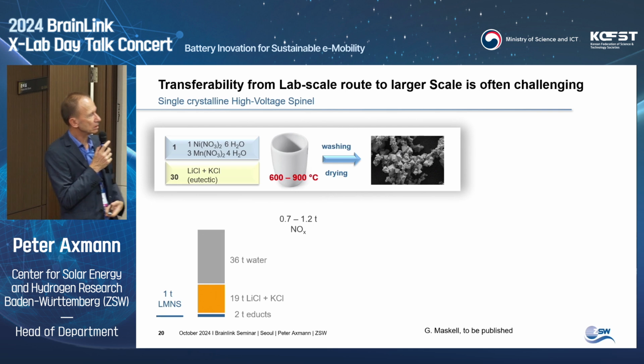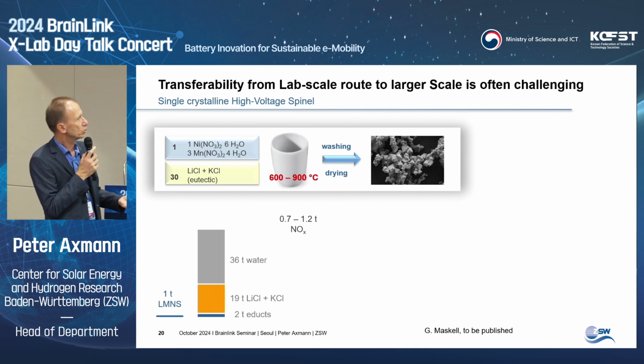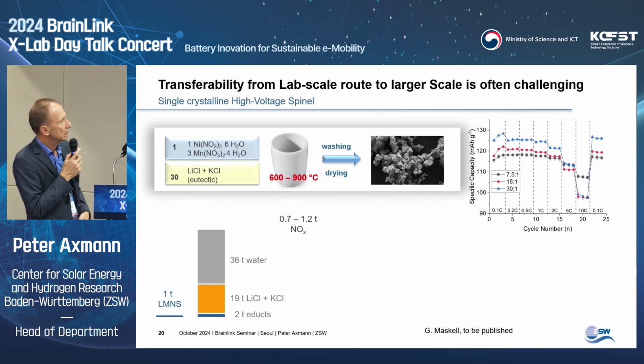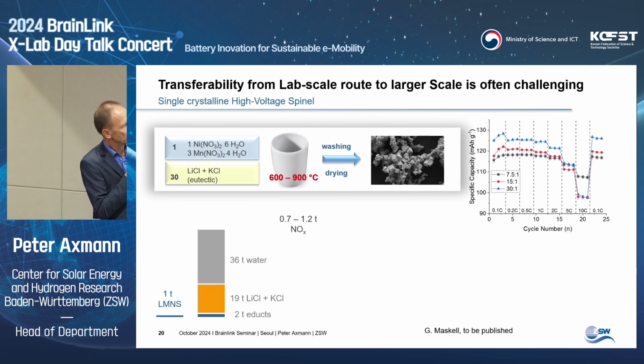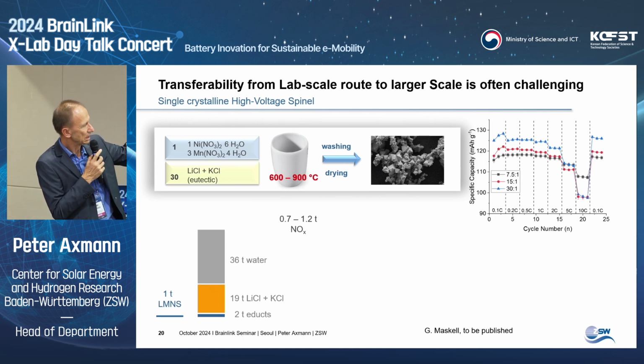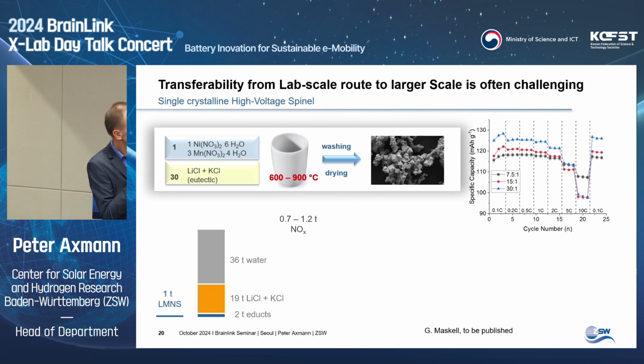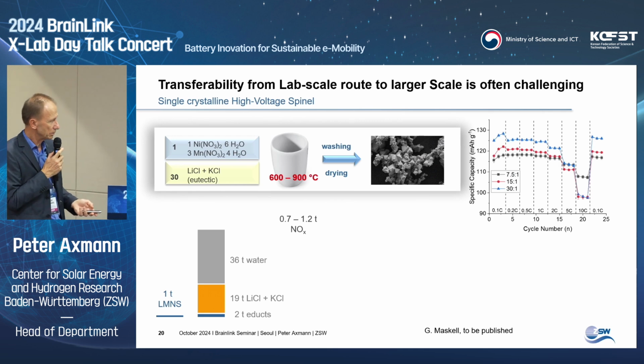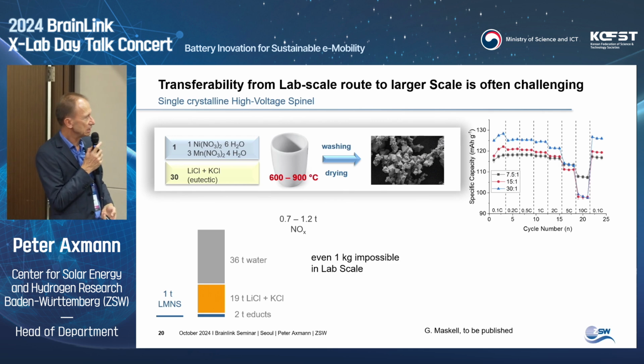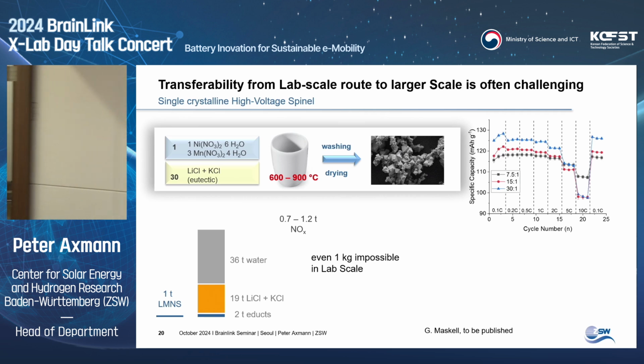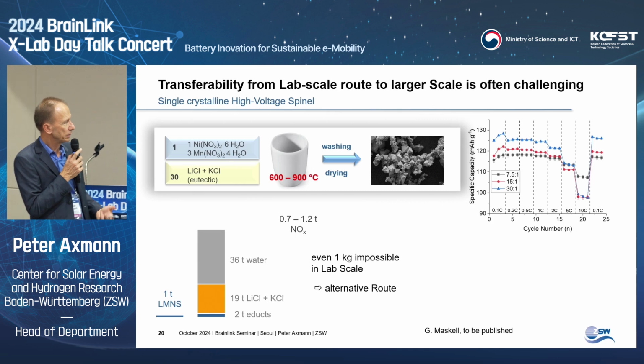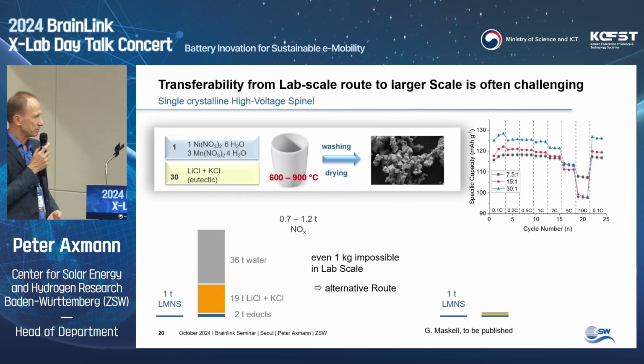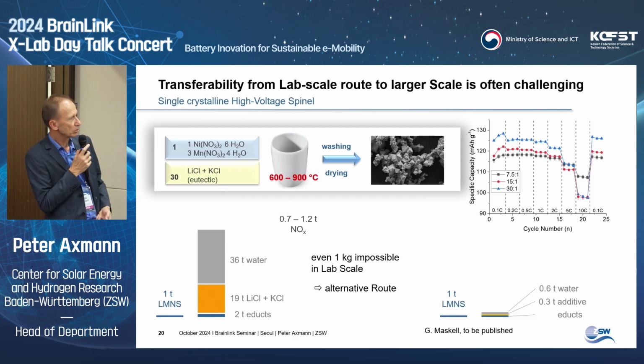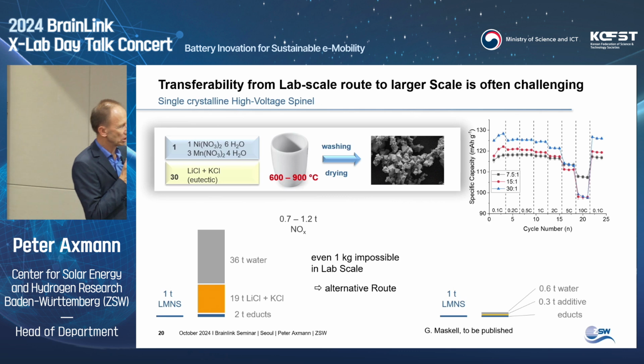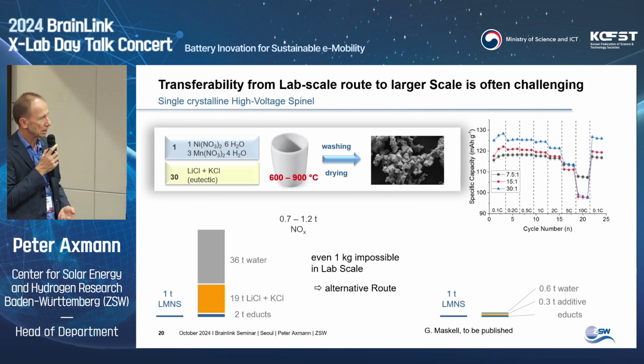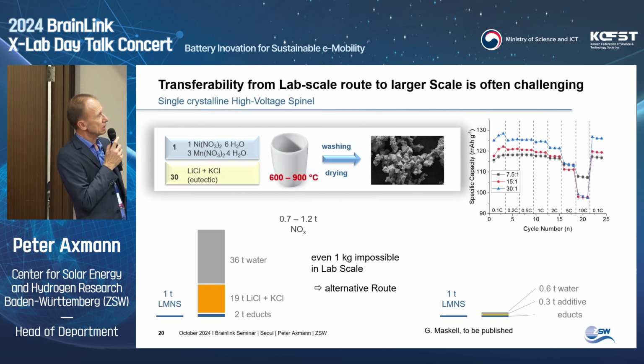It's quite a lot. In addition, you produce a lot of nitrogen oxides, which you have to release somehow or get rid of. And what we see here are the capacity curves, the blue one with the original recipe, and if we try to reduce the amount of this unwanted lithium chloride, potassium chloride, we see that capacity and performance go down drastically. So this is not the way to make the material better or to make it in large amounts, and we see even 1 kilogram is impossible to make at lab scale. We can go to alternative routes, so this is possible, but we have to change this. And so we developed a route which we'll publish soon. For 1 ton of LMNS we can go with 0.3 ton additive and 0.6 ton washing water, very easily to more than 1 kilogram in our scale. So this was just to show the way is not too easy.